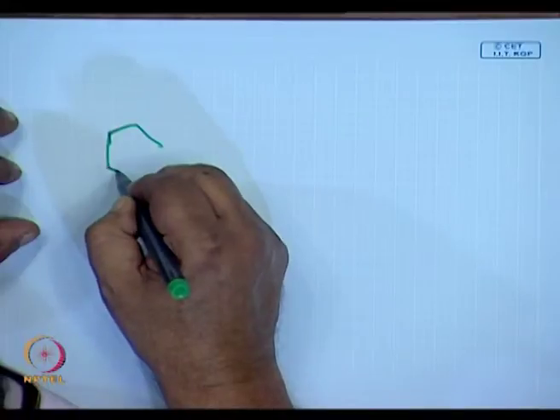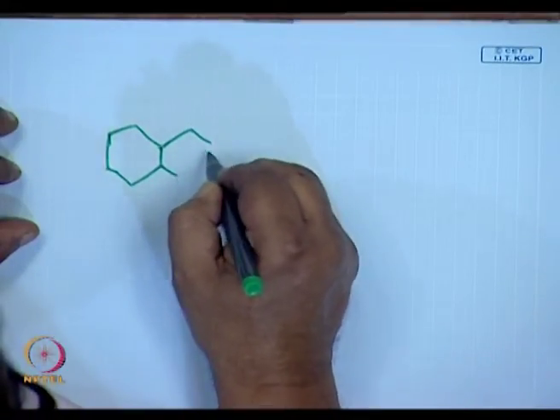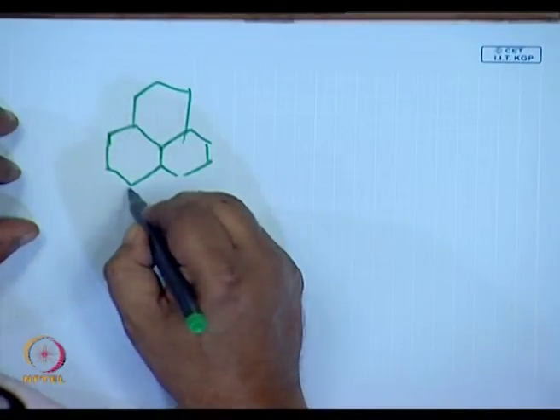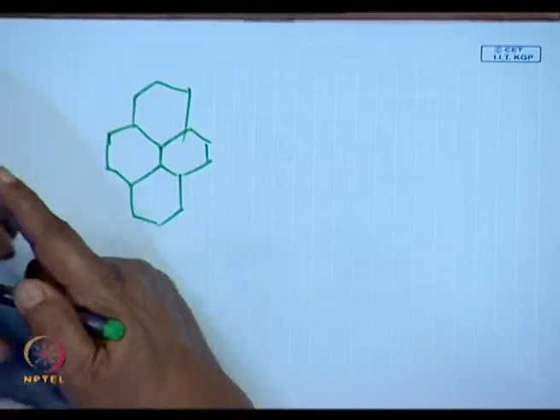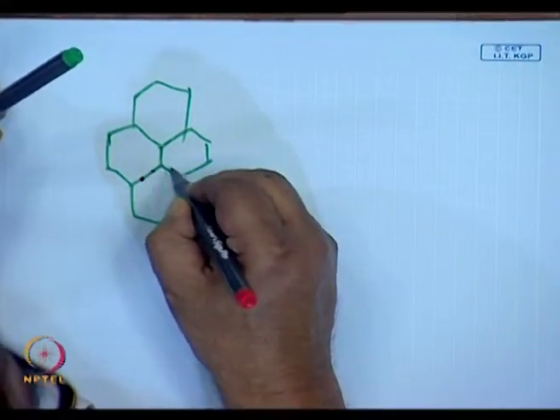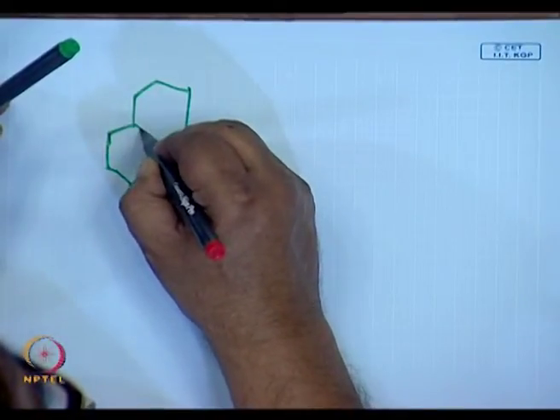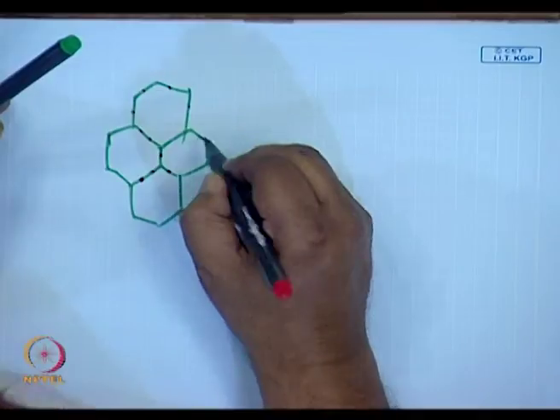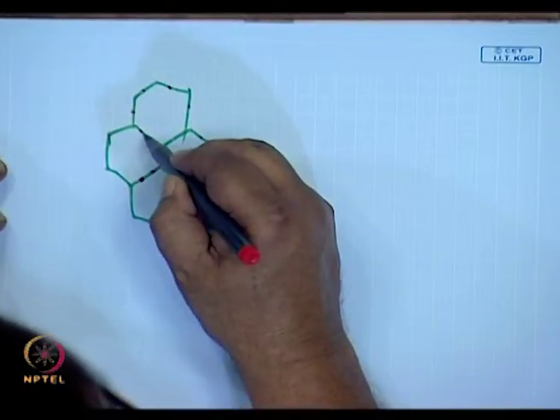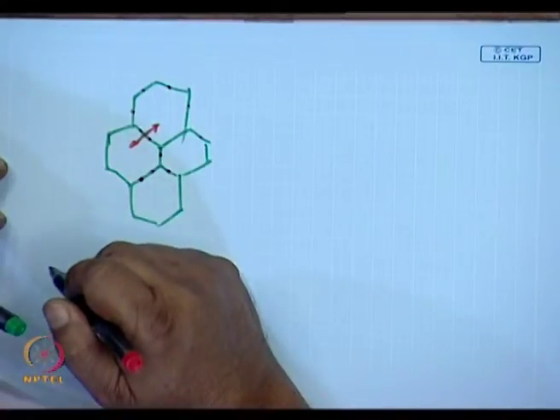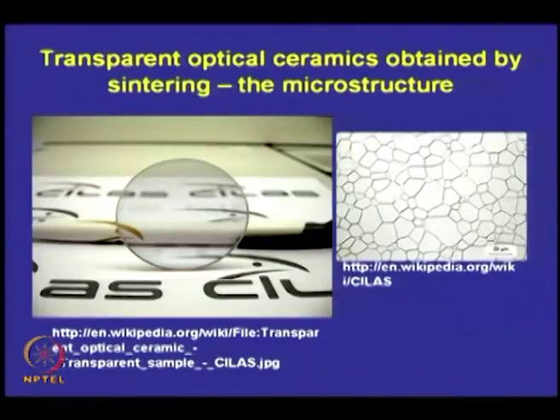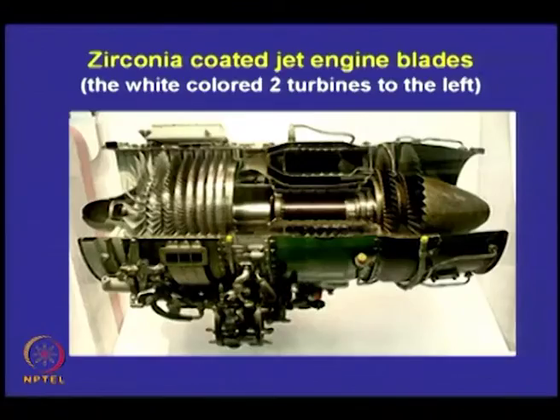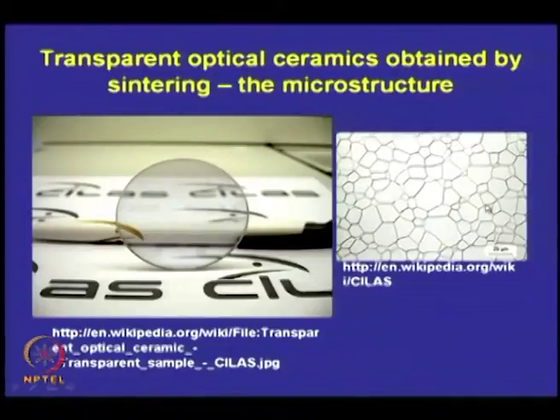Just using hexagons to make sure I've got a reasonably uniform microstructure, though that is not always true - what happens is these grain growth inhibitors grow on the surfaces, and as a result they prevent the grain boundary from moving either way, thus retaining the fineness of the microstructure which you see in this slide to your right. This grain growth inhibitor has made this transparent alumina possible.